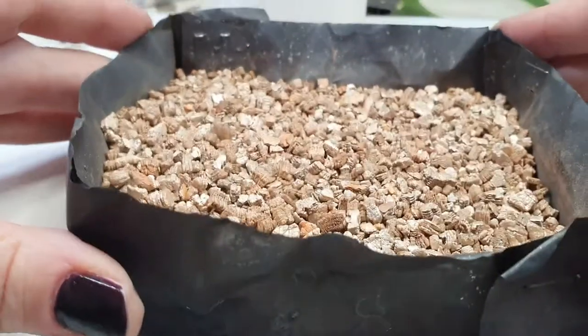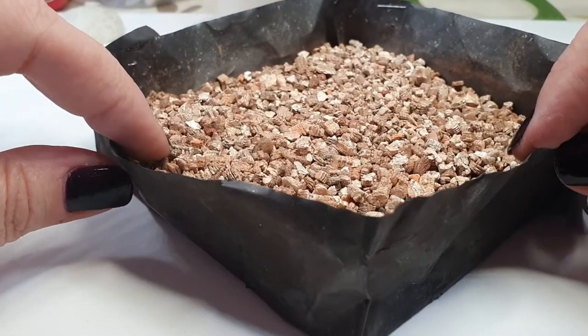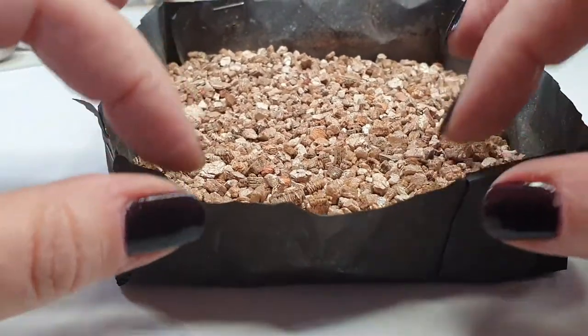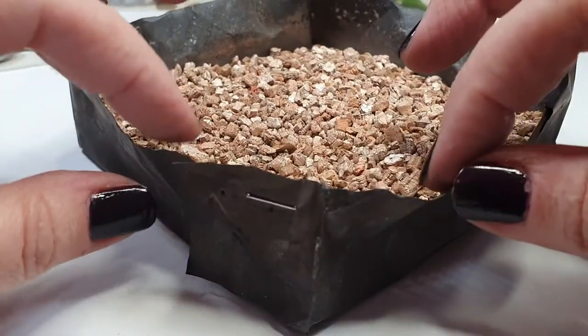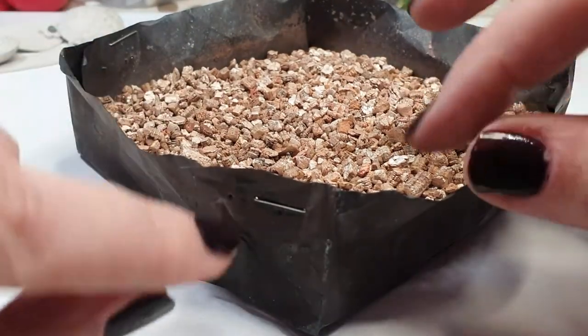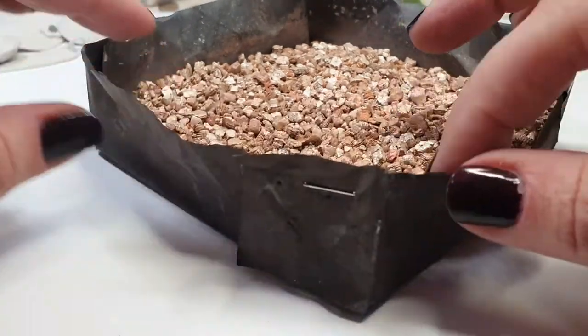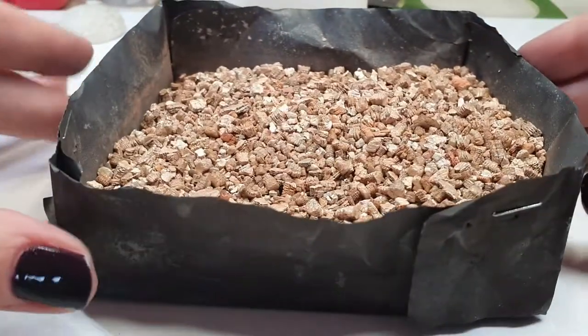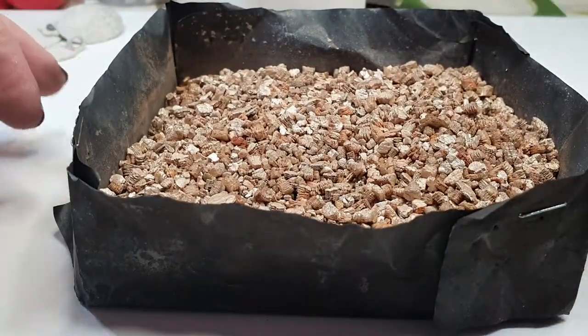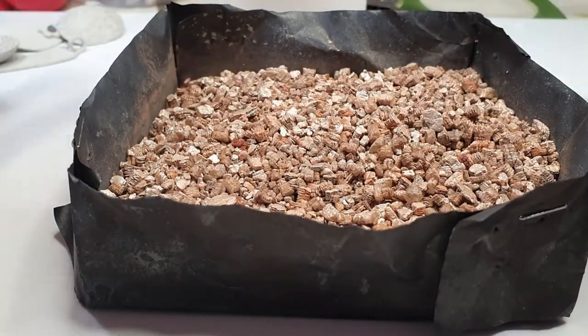I also have a larger box — this is a steel box made from no-flake foil, and it's lasted me 10 years. It does a great job and basically does what it says: it doesn't flake in your kiln, unlike stainless steel which can flake off. You build the box and fasten it with staples; occasionally the staples burn away and you just replace them. It's not a thing of beauty but it's very useful, and it gives me a larger area so I can fire more than one object at once.